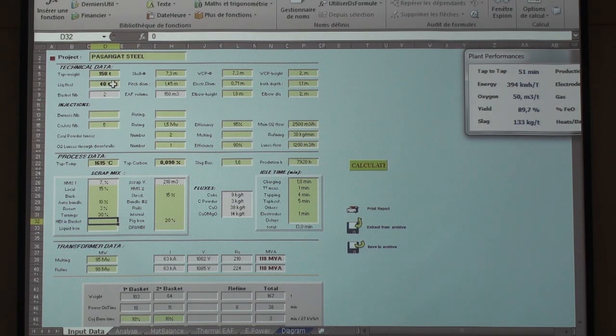There is a critical size. For the DRI, if you go to, let's say, 90% DRI, you need to increase the hot heel, because you have no time, not of, let's say, heat. A lot of liquid steel is generated by the early melting when the electrodes are going down. This is something we will see with the ECS training: the boring phase should be at very low speed to enlarge the pit around the electrodes, and then you can create more liquid steel there.